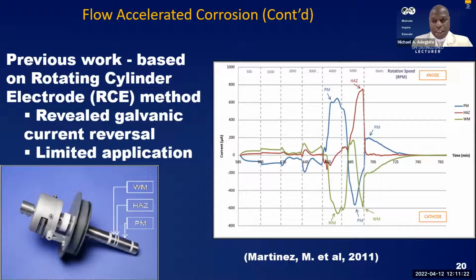Looking at the graph on the left-hand side, you will see a sinusoidal, a reversal of current of the galvanic current wave. So the current, the blue indicating the parent metal, the heat affected zone is the red, and then the green is the weld metal. So you can see the reversal, the sinusoidal nature. And whenever we are above the 0 level, that is when we have the anode. Any region above the 0 positive current here now is the anode, that is the metal goes into solution, the component that goes into solution.